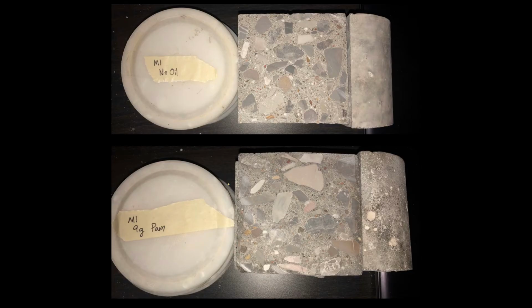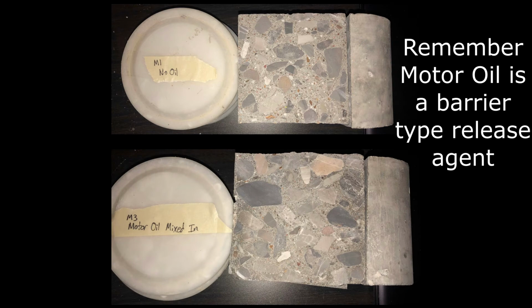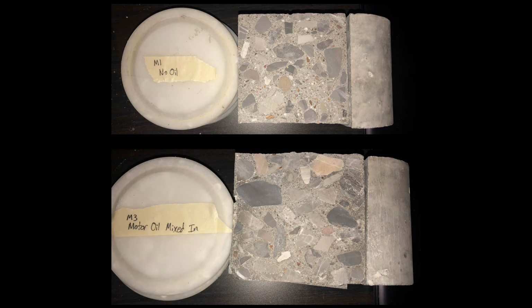Now, if we take a look side by side of no oil whatsoever and the 9 grams of PAM applied to the cylinder, you can see the surface area of the concrete, how it goes from really smooth to the PAM just eating away at it. If you look at the no oil compared to the motor oil mixed in, again, you can see how the no oil has relatively no lines around the aggregate, but you can see in these areas that there is a fine white line around that aggregate that the motor oil has started.